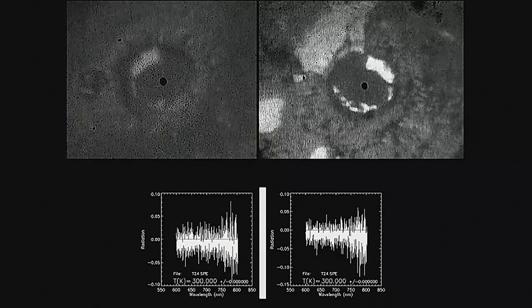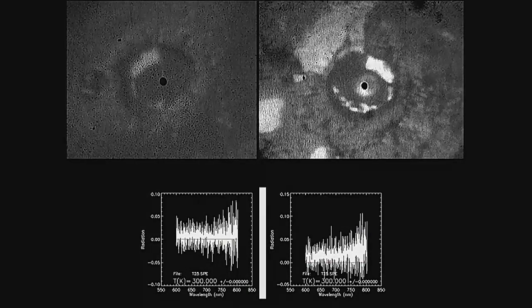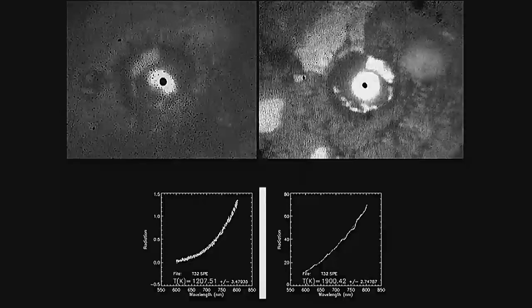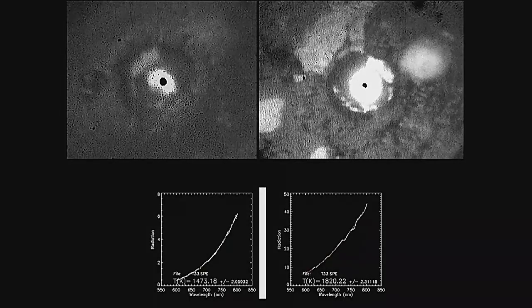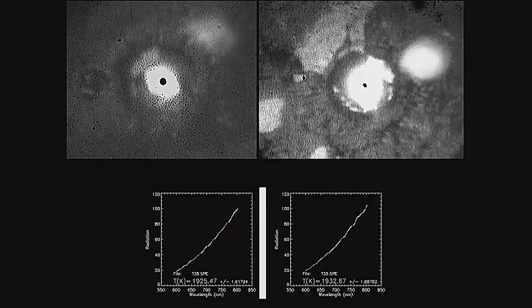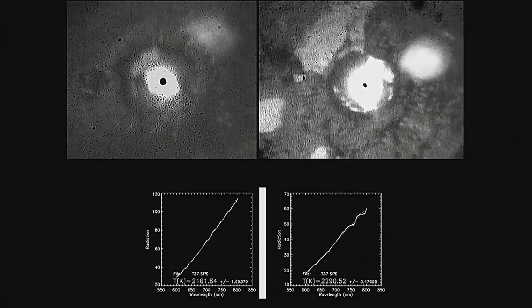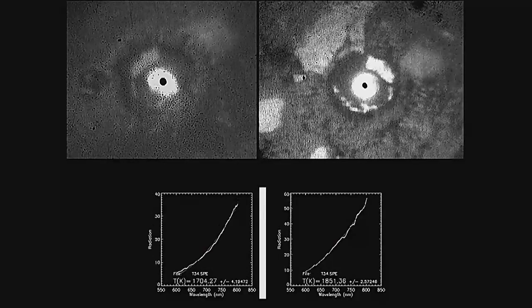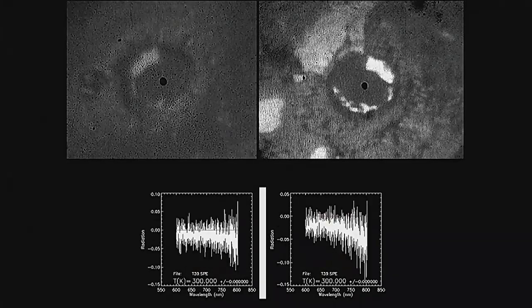That's how it looks when you actually do the sample. You start putting more and more power. The sample starts coupling. It literally glows. You collect that glow. It's black body radiation. You fit it to your standard, and you calculate temperature. So you see, this isn't exactly putting a sample in a large furnace. You have a portion of the sample that glows, and the next micron is cold, at ambient temperature or nearly. So you can have temperature gradients of almost 1,000 Kelvin across a few microns. So your sample is going to be really